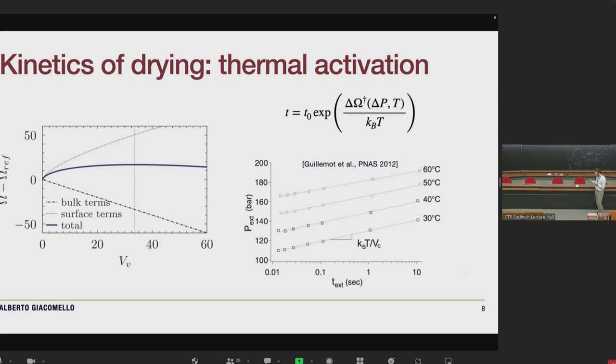The other thing one has to keep in mind is that drying is really a nucleation phenomenon in which you have to generate a bubble. You have the usual competition between bulk and surface terms which gives rise to a free energy barrier. You can see this as a signature. If you do constant frequency experiments, you cycle intrusion and extrusion, you see that the extrusion pressure depends on the frequency or on the time of your experiment and also on the temperature. You really have a thermally activated signature of this process.